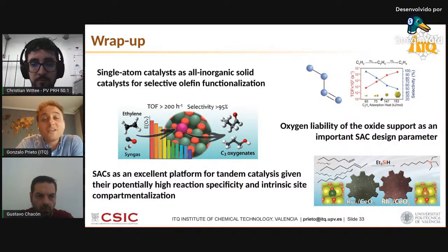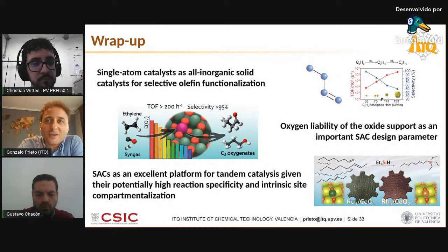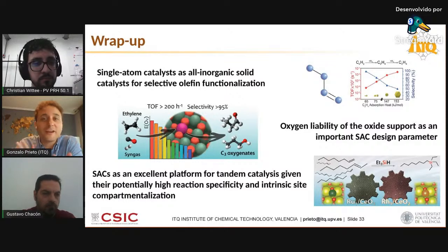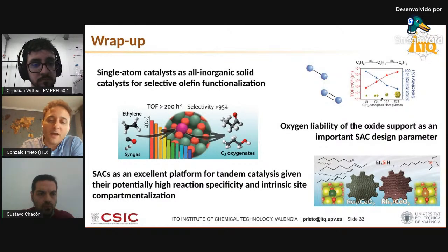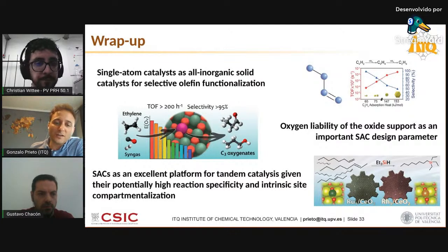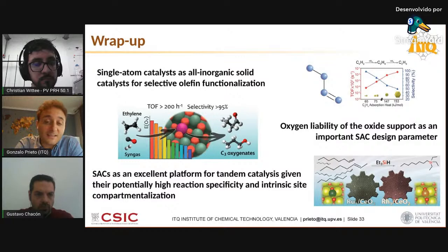Yes. Well, I have to say that tin oxide is an oxide with intrinsically low Tammann and Hüttig temperatures, so it is very easy to sinter. And the way we are synthesizing our single atom catalysts is by annealing them at high temperature. So by improving the specific surface area, we might not be able to achieve terrifically high surface areas, but perhaps slightly higher. More than a surface area, I am interested also in terminations, etc. How can that affect the way rhodium atom centers sit and behave?